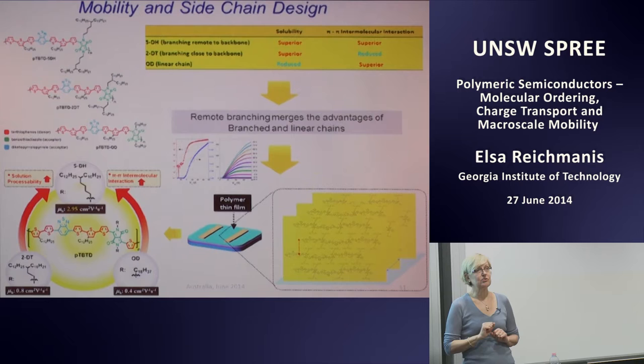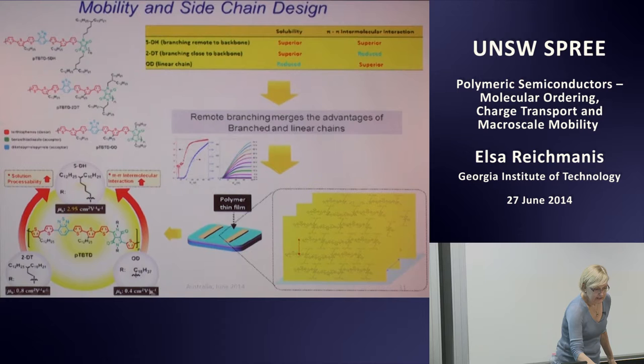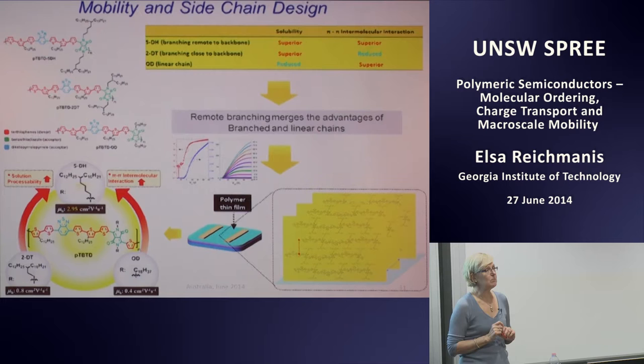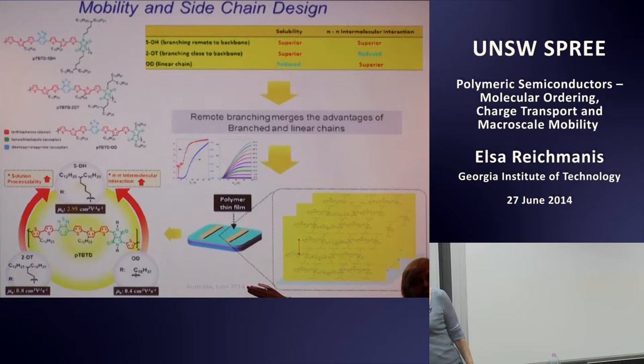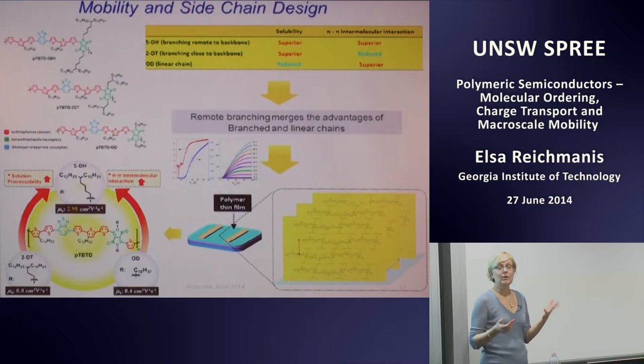All right, so the linear material, which is not very soluble and as a result is a little bit more difficult to handle, has a good mobility, but not a great mobility. The mobility there for hole transport is 0.4 centimeters squared per volt second.